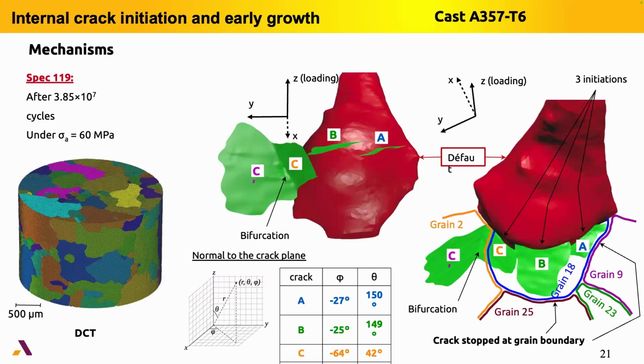So if you look at the microstructure and the cracks in this specimen, we obtain at the beginning the following 3D configuration. There are the 3 cracks, A, B, C. And you can see here that the cracks A, B, C are all in one grain, number 18. So the question is why only one crack, the number C, was propagating in the neighboring grain, here, number 2, but not the others in the neighboring grain.